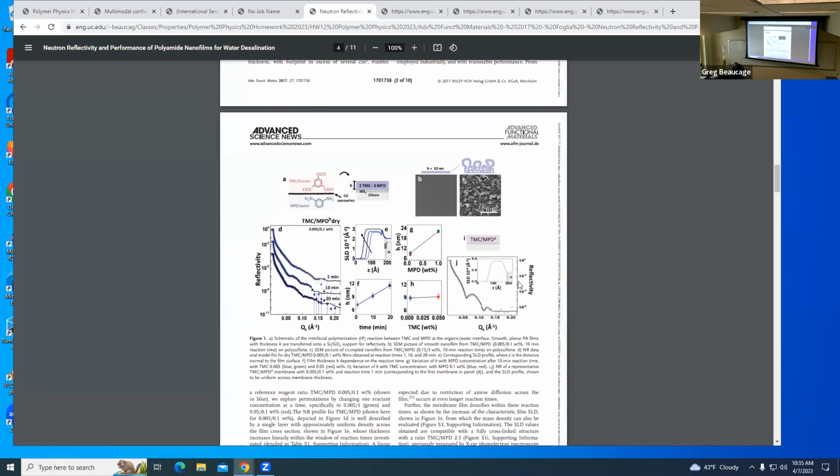This is a reflectivity curve. So that's the intensity that came in, I naught. So when you get to the critical angle, the beam that came in bounces right off. So below, I think it's 0.2 degrees on silicon, it's a grazing incidence, so you get full intensity out. Take that intensity, and as you go up, you get beyond the critical angle, and you start to probe the surface. So the ratio of the two gives you this reflectivity.